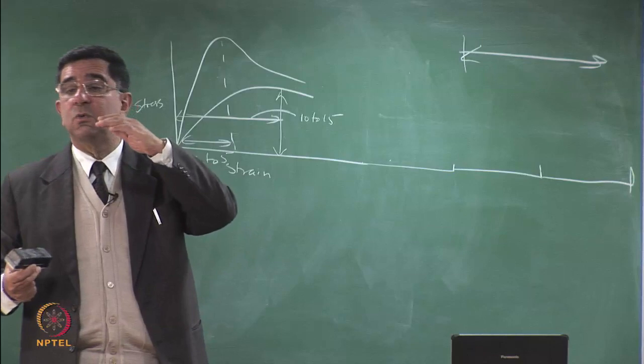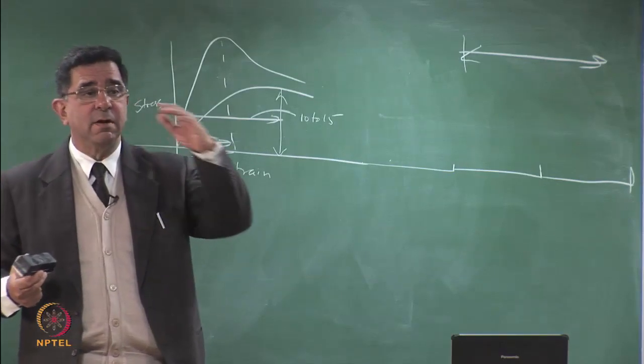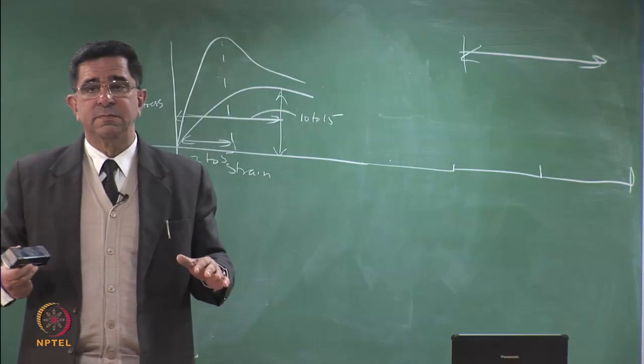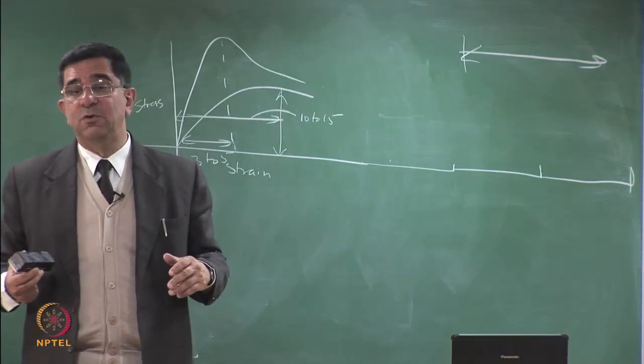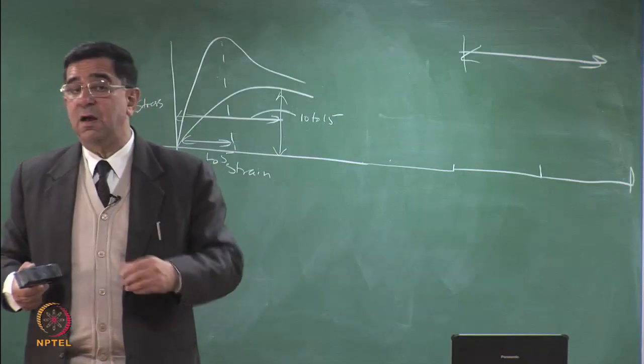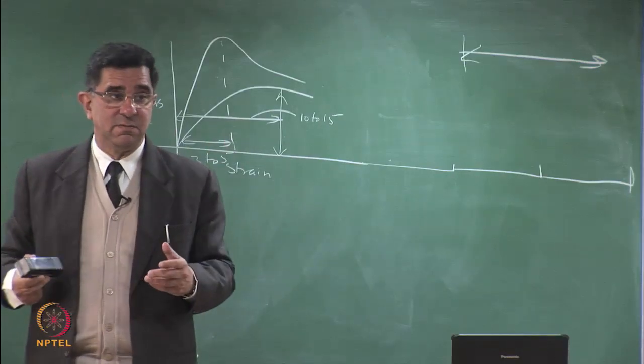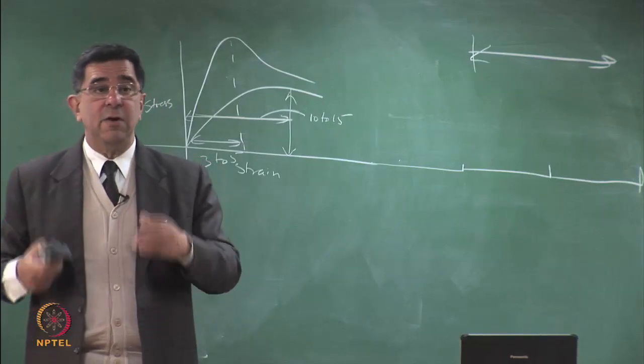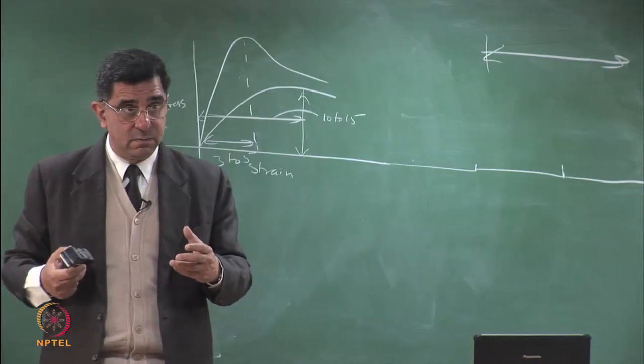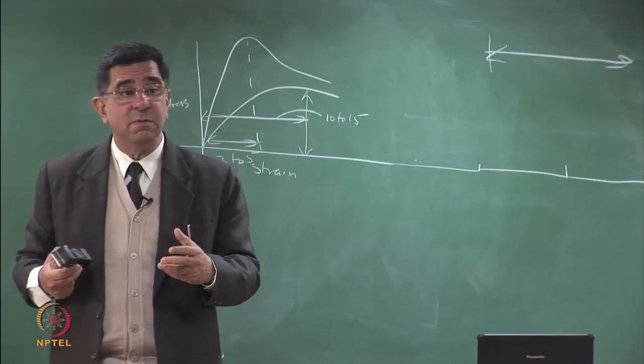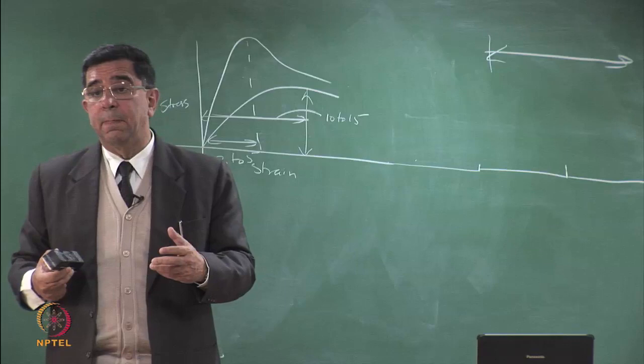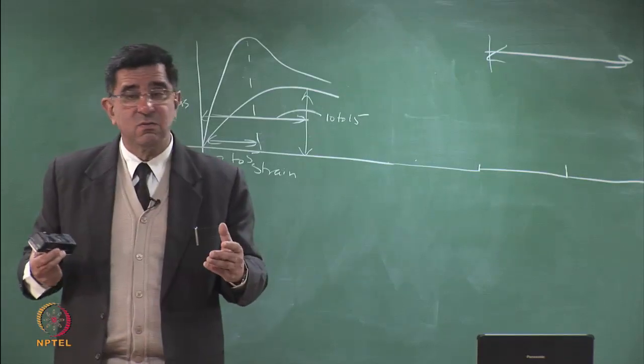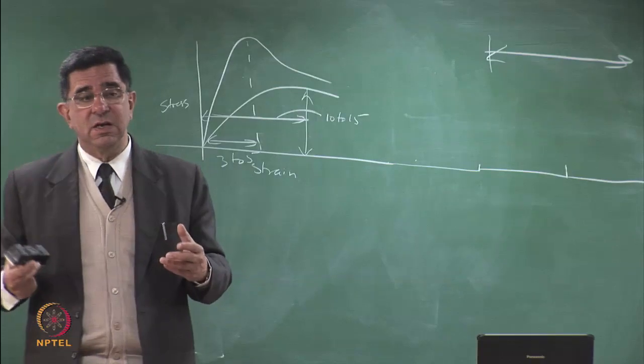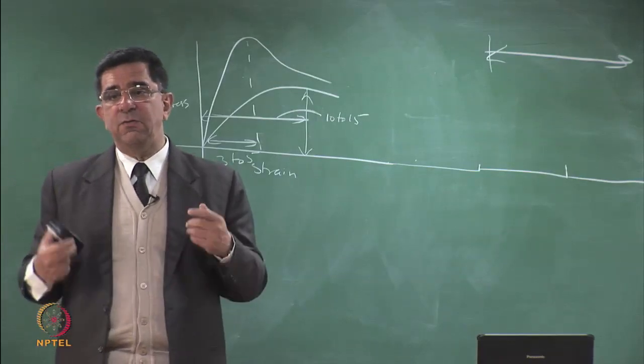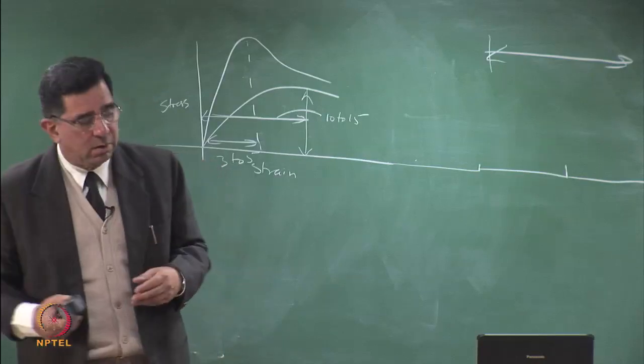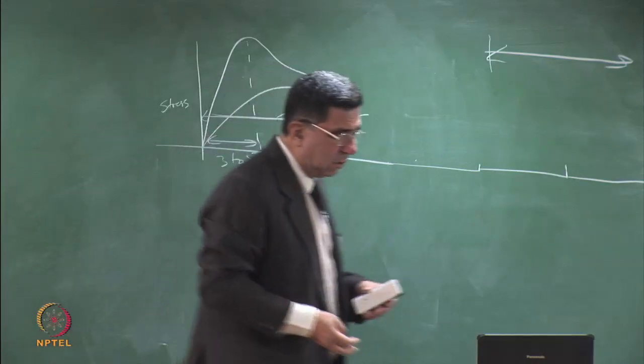So maybe which has more settlement, cover or liner? A liner has more settlement because the stresses are higher. But a cover has more settlement because there's biodegradation. So in municipal solid waste landfills, where the biodegradable content is higher, cover settlements can be very large. But if you have inorganic waste, which does not settle due to biodegradation, then maybe the liner settles more. But if you are going to have very large settlements, then you will use LDPE polymer. Okay, so